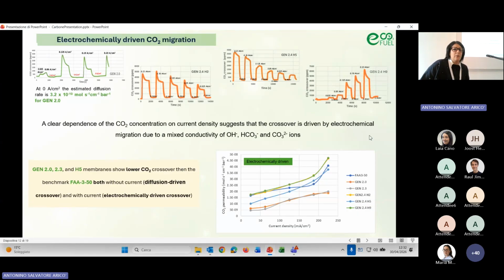The same test was carried out for the selected Gen 2.4 membrane and Gen 2.0 membrane. We can see that for the Hydrolyte membrane, we reduced the crossover by 1 order of magnitude because we reached 10 to minus 10. And for the other membranes, the crossover is similar. In addition, in this graph, in which is reported the electrochemically driven crossover as a function of the current density, we can see that membranes 2.0, 2.3, and H5 have a lower crossover than the benchmark, while the other two have a little bit higher crossover. But in any case, the value of the permeability crossover, as we can say, is in the order of 10 to minus 8. So it is not a big amount of CO2 that migrates to the other side, so it is not really affecting the performance.